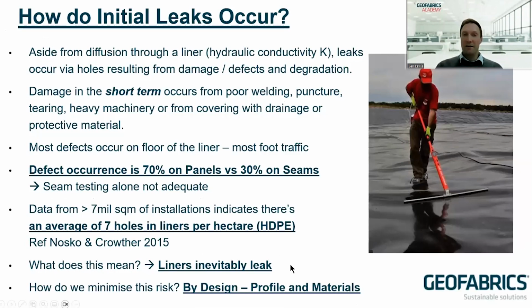How are leaks occurring? They're occurring either through short-term damage or long-term degradation damage. And in terms of the short-term damage, it's occurring from poor welding, puncture, heavy machinery. Could be drainage you're placing over the primary liner, or even placing protective material over the top. You can damage while you're placing it. So it's generally an installation process. It's worth noting most of the defects are occurring on the floor of these assets through foot traffic or machine traffic, and also that 70% of your defects occurring on panels between welds, while 30% are only on the seams.